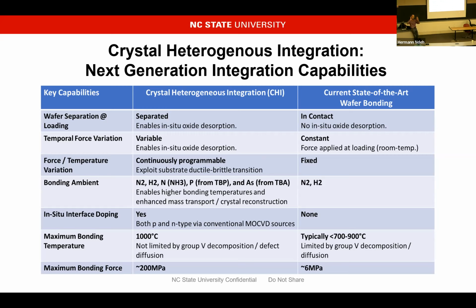So one of the things you might ask is, well, you've got that bowed wafer, how do you deal with that? What we do is we heat the wafers up to a point where we get past the ductile brittle transition. And when we do that, then we apply force, and in doing so, we can basically flatten out the wafers. That works for gallium nitride. It turns out we found that around 800 degrees C or so we can get past the ductile brittle transition for gallium nitride. It obviously doesn't work for aluminum nitride. That's much higher temperature. So there's still more to be explored there of what it means for some of the alloys as well.